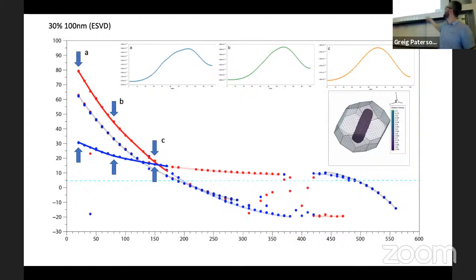relaxation time. And then this little grey dotted line is lab time, which is supposed to correspond to about 100 seconds or so. What you see is some really complicated stuff going on at a fairly low temperature, around 150, and then there's another blocking temperature happening at around 500. Some really complicated behavior happening there. Is something like this going to be the cause of a tail?